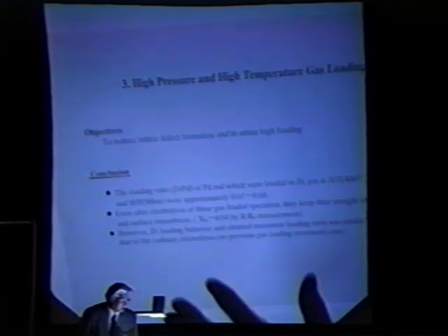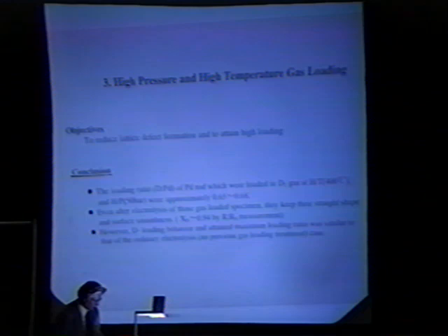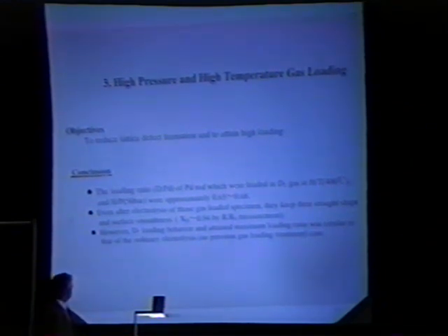So we would like to conclude this experiment. The loading ratios, which were loaded in deuterium gas at high temperature and high pressure, were approximately 0.62 to 0.68.